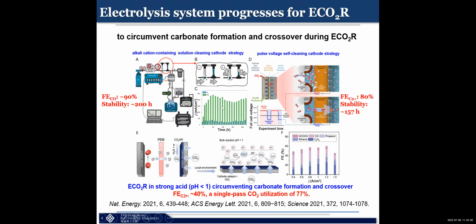So the other approach is about using a pulse, okay, for C2. This is not exactly for C2H4. This process is for CO, but it introduced some new ideas. They talk about minimizing the alkalis, and then flushing with water for a certain period of time, and then they can reduce the formation of the carbonate. Okay, so eventually they can increase the stability for the reduction of CO to close to 200 hours, with the C2 Faraday efficiency growing to 80%.